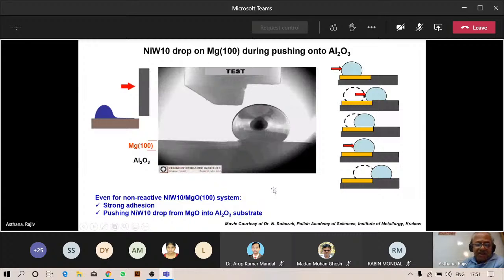Even though the system that we are looking at, nickel tungsten on magnesium oxide, is a non-reactive system, the droplet doesn't want to leave magnesium oxide because the wetting is good, even though it's not a reactive system. So this kind of pushing of liquid is possible with this kind of instrumentation. And after you push the liquid away, you can look at the interface underneath the droplet.